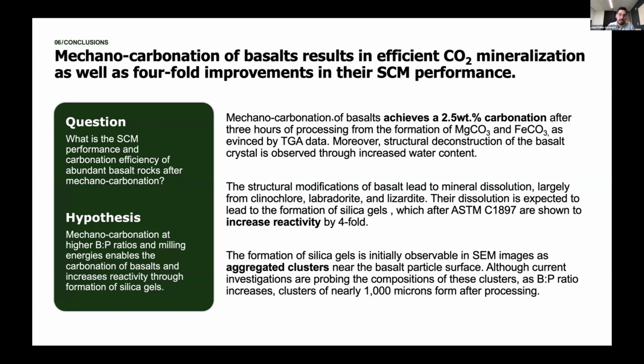And very interestingly, these aggregated clusters from SEM images show that these clusters could have a really important role to play in the mechanisms by which this mechanical carbonation is happening, and that the formation of silica and carbonates is interlinked. And we're exploring that mechanism a lot more in our investigations currently. But we hope to be publishing these in the next couple of months to share with everybody and really understand the mechanism so we can engineer this process for improved efficiency and large scale deployment here in the US.